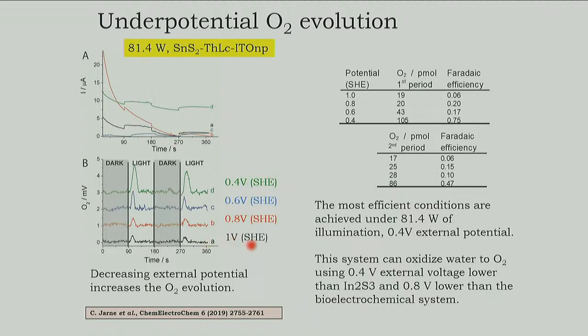So we started to decrease the potential to see what happens there, and also the light intensity. Now at this one, we could see that if we decrease the potential, the oxygen signal we're getting in our sensor was going up. And we could see that the Faraday efficiency and the oxygen produced was bigger. So we found out that applying a very high potential is not more efficient, it's also damaging the enzyme and is making secondary processes that we didn't have any way to determine what they were, probably photooxidation of the material, but it was working much better with lesser external energy application to the semiconductor in terms of electric potential.